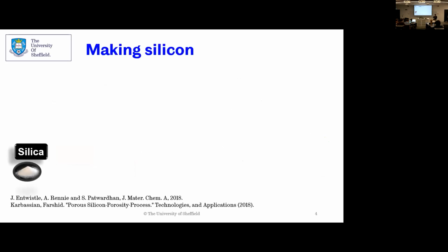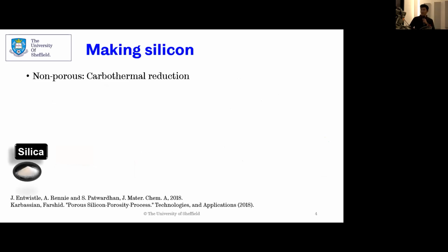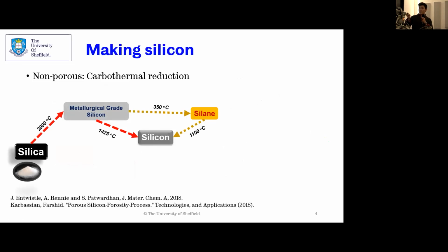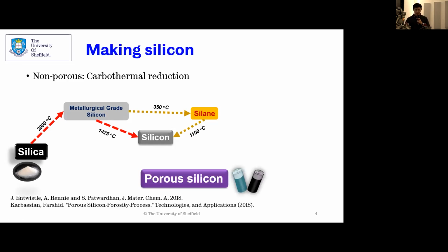Silicon is mainly made for the transistor market, so chips, processors, things like that. And it's made by a non-porous route, the carbothermal reduction. This requires 2000 degrees Celsius, plus some further processing to make it pure enough to use for chips. But this is actually not good enough for batteries. It's not porous. These temperatures are well above the melting point of silicon, so the pores get destroyed and you get sintering.